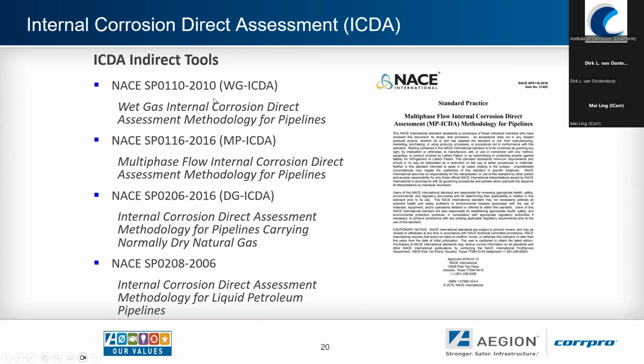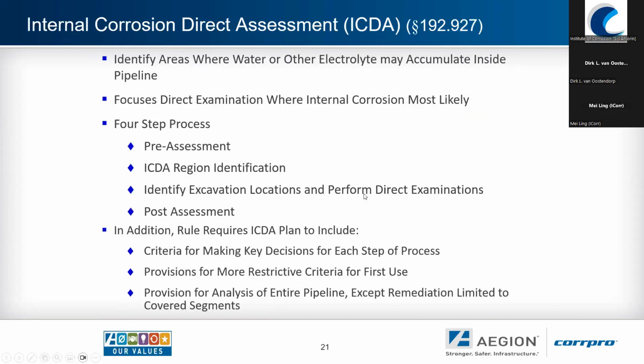After that, we understood the differences between wet gas, for example, multi-phase flow, and then finally, there's a condition where if you have large cross-country gas pipelines that are transporting what would be considered normally dry gas, with the exception of, let's say, dehydration interruptions or anything like that, there was a separate recommended practice, standard practice that NACE released for these. So from the ICDA standpoint, there are four different standard practices to follow depending on the conditions of the pipeline that we're going to be looking at.